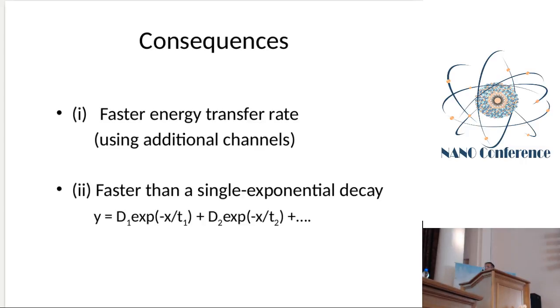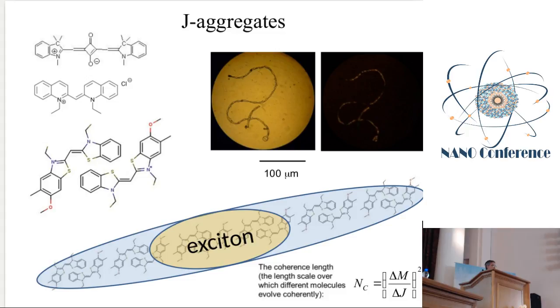So I will consider large aggregates based on specific molecules. For example, these cyanine molecules, which are polar molecules and which can form so-called J aggregates. In principle, J aggregates can be composed of dozens or even hundreds of molecules, which have nanometer or even micrometer sizes. But when we excite an exciton in these J aggregates, we can excite at least several molecules concurrently. They will be excited in the same phase. And this is the specific of exciton in J aggregates, because this exciton has high energy and it can migrate along the J aggregate ensemble.